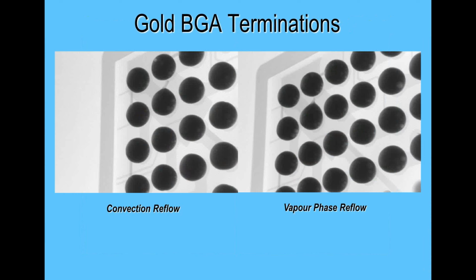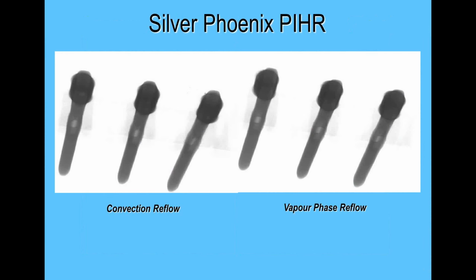And just some examples or comparisons, if you like. Reflow soldered with convection and vapor phase, all the joints are perfectly the same. They're good, reliable solder joints. You might see a slight improvement in wetting if you compare vapor phase over convection, depending on the PCB finish, and this would normally be shown up by the wetting indicators.